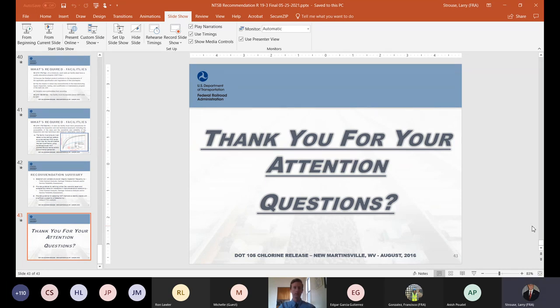So what I would say is that the level of demonstrated skill required of a technician must be stated by the owner and must be demonstrated by the tank car facility through the development of a procedure for evaluating the operator's skill. We mentioned the 29-29 experiment. If you look at ASME Section 5, Non-Destructive Evaluation, Article 14, they show what the different non-parametric binomial values would be. For example, 7 out of 7, I believe, is a 90% POD at 50% confidence that an owner could accept as their level of capability, or the level of capability they require for facility personnel to achieve.